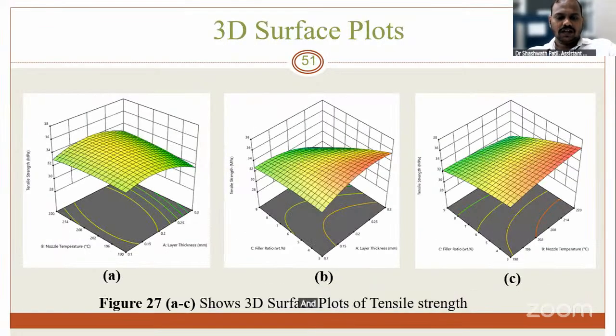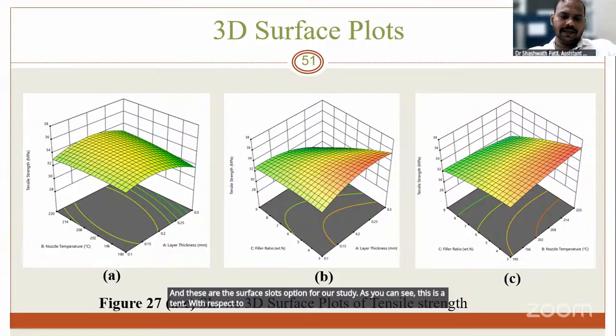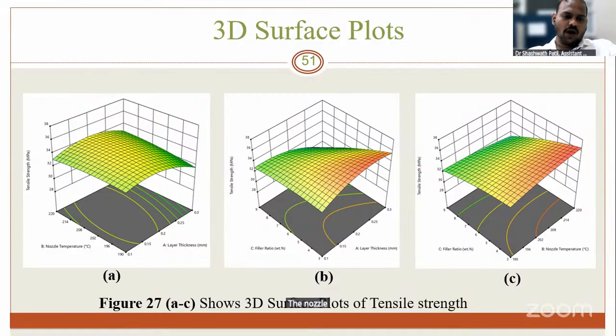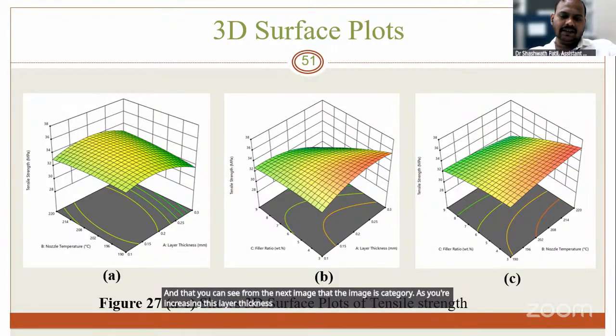These are some of the surface plots obtained for our study. You can see the tensile strength with respect to nozzle temperature and layer thickness, filler ratio and layer thickness, and filler ratio and nozzle temperature, keeping the third parameter constant. As the layer thickness increases, at a moderate nozzle temperature of 210 degrees, we achieve the maximum tensile strength. In the next figure, B, as the layer thickness and filler ratio increase, the strength reduces. So at a moderate 6% filler and a layer thickness of 0.2, we get the maximum tensile strength.